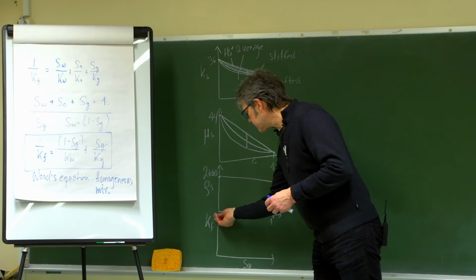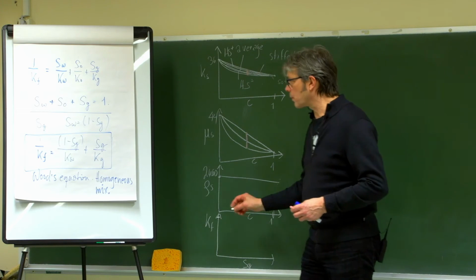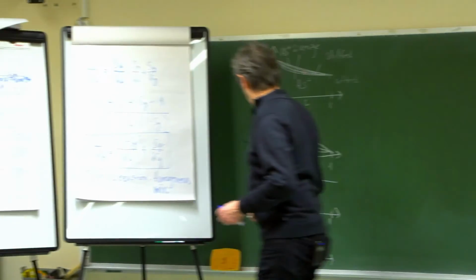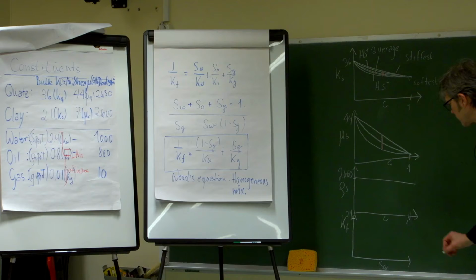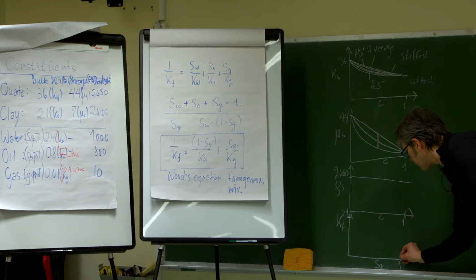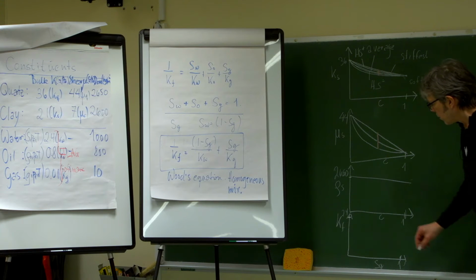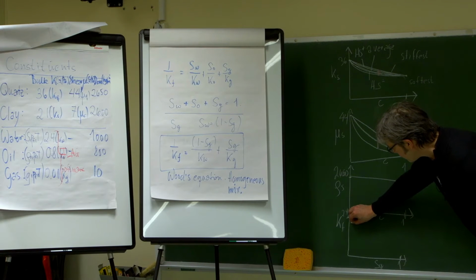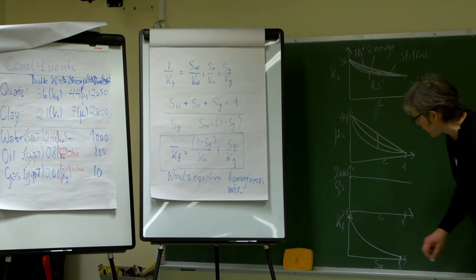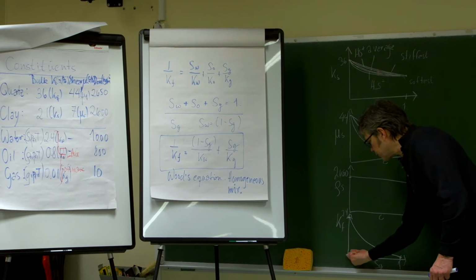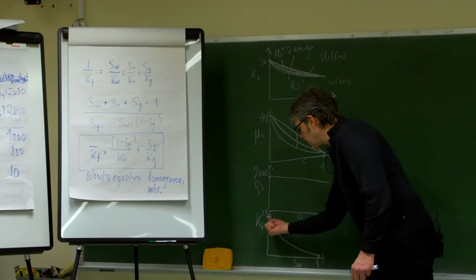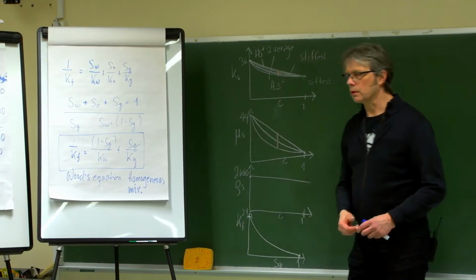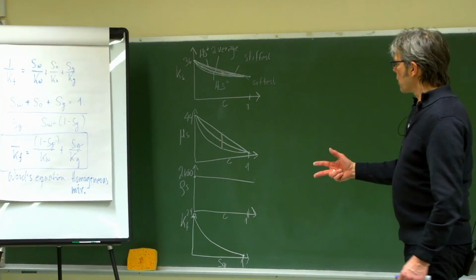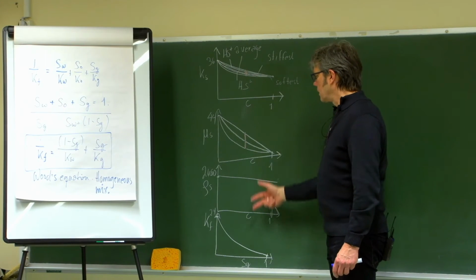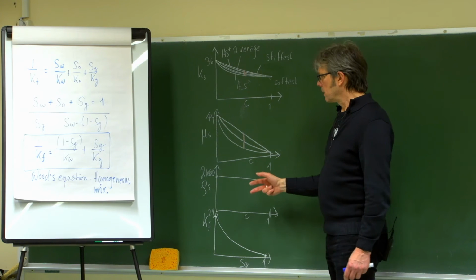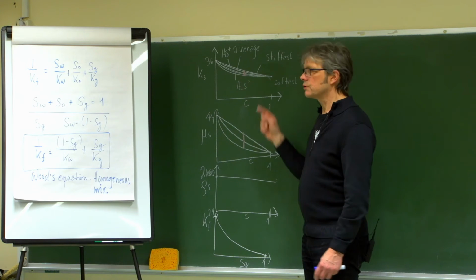And then we have the fluid properties. For zero gas fraction, it's 2.4 here. The other end, at fully gas saturation, it's very low down here. So you see that it's quite some contrast, and if you use the Reuss or Wood model, it gives you a change like that. Worth noticing that just a few percent of gas in water makes a huge effect on the fluid bulk modulus. So these are background functions that we will now use. It's easy to go back and update our model just by picking values here, as I will show you.